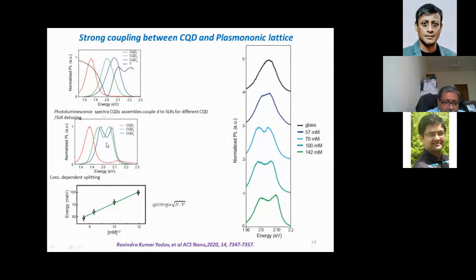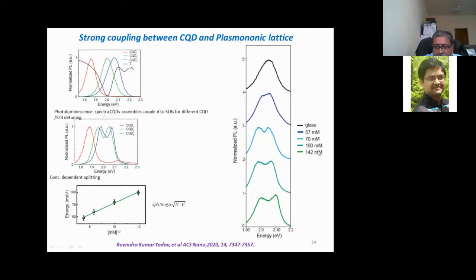When you couple them, this is what you see: a strong splitting, which is indicative of the emergence of strong coupling. Another signature is that when you plot this as a function of concentration, it should show the square root scaling, which is what we see. So that is good. We are able to use concentration to enhance this interaction. If you see here, it goes from what you see on glass, which is a boring substrate, and then you keep seeing the magnitude increasing as you increase the concentration. Now, is that all?